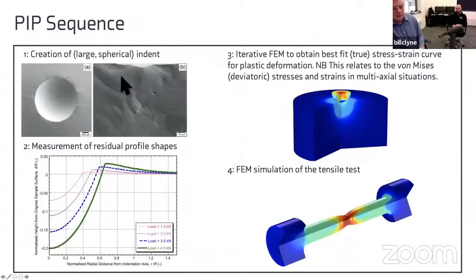So just emphasizing again the sequence, you create the indent using a large spherical indenter. You measure the profile. Here's some different profiles for different applied loads. If you're interested, you can start focusing on looking at the microstructure around the indents. This is showing these persistent slip bands in individual grains, so you can get some feel for what's actually going on inside the material. But the key procedure is then to repeatedly simulate the indentation process, and as I say, get the best fit between the measured and modeled profile, and then that gives you the true stress strain curve. That's what we're trying to obtain.